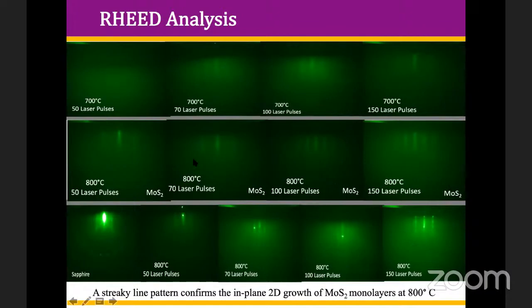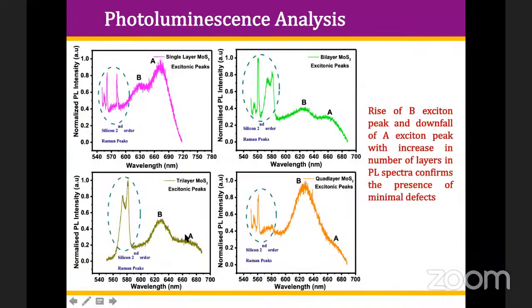And these are the RHEED patterns at 800 degrees Celsius, on sapphire substrate, which clearly shows that the patterns are very streaky, very sharp. This shows that the MoS2 monolayer has been grown at 800 degrees Celsius successfully, and the crystallinity is very, very good as compared to those systems obtained by exfoliation. In exfoliation, you can't perform the RHEED analysis. RHEED analysis can be performed only in situ when you are depositing the material atom by atom or molecule by molecule.